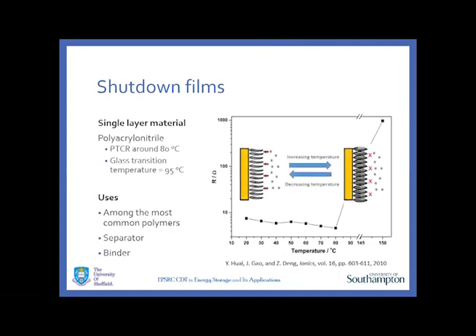And then that's the figure showing the operation I would like to observe. When you increase temperature, you get a swelling of the polymer film, which prevents the ions from reaching the surface. And then ideally, when you decrease the temperature, it becomes reversible and it will retain its operation. With melting transitions, this will not be observed because you've irreversibly changed structure. With a glass transition, this is potentially possible. I have not yet observed this in my research, but if I can achieve it, it'll be possibly groundbreaking. It would be very nice to achieve.